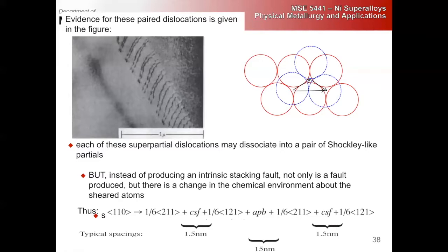And of course, these faults all have different energy, right? So the separation of these partials is going to be dependent on the energy. So these complex stacking faults are higher in energy. They're going to be much narrower. These Shockley partials are going to be much closer to each other than the ones that create the antiphase boundary, right? Roughly about 10 times as long, right?